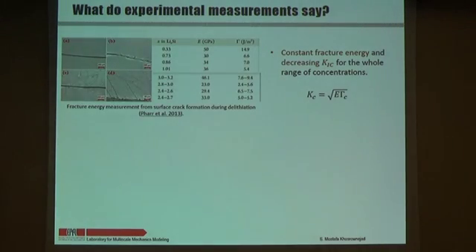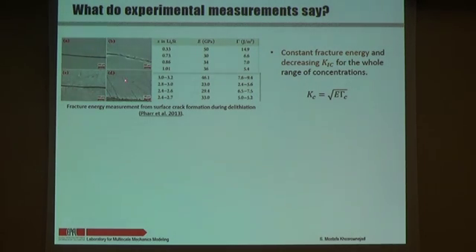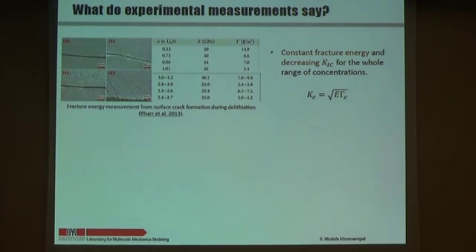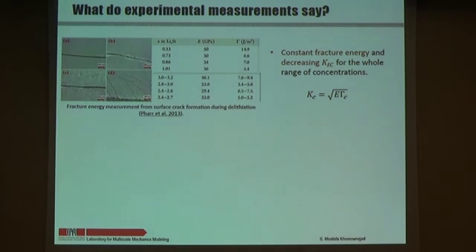So we need to understand this. There are a few experimental studies on understanding the fracture properties of lithiated silicon, but they are not direct measurements of fracture properties. For example, one study calculates fracture properties based on measurements of the fractured surface of a thin film during discharging. If you discharge the system you create tensile stresses and cracks appear; they calculated the fracture energy and saw an almost constant fracture energy for different lithium compositions.